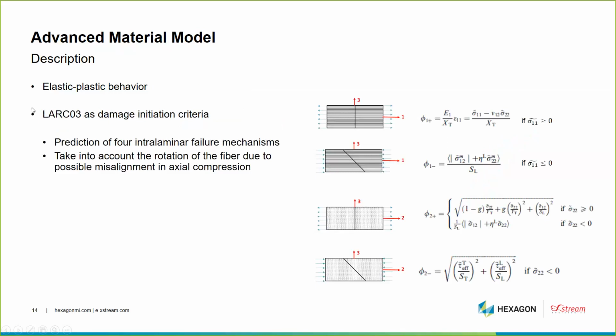Second ingredient of the numerical model, we use LARC03 as a damage initiation criterion. So LARC03 is already something well established in the community, and it's a failure criterion that allows us to predict intralaminar failure mechanisms. LARC03 also has something which is extremely interesting, which is that it takes into account the rotation of the fiber due to the misalignment in axial compression.